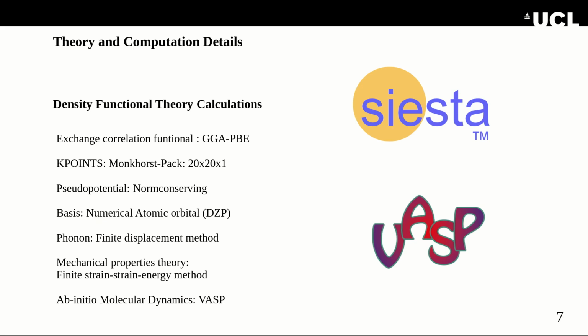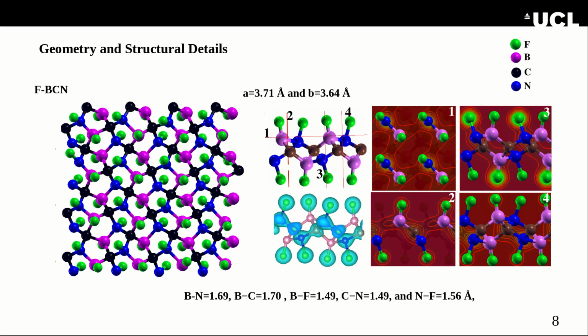We perform the density functional theory calculations using the code SIESTA mostly, and we use VASP for ab-initio molecular dynamics calculations. We can see the fluorinated boron carbon nitride, and we designed this compound by passivating fluorine partially on the top and bottom layer of the pristine BCN, which is composed of three elements, boron, carbon, and nitrogen. We can see the different planes and the corresponding bond analysis by the Mulliken charge analysis calculation. We found that the boron-nitrogen, boron-carbon, and boron-fluorine bonds are covalent in nature, and the carbon-nitrogen-fluorine is ionic in nature.